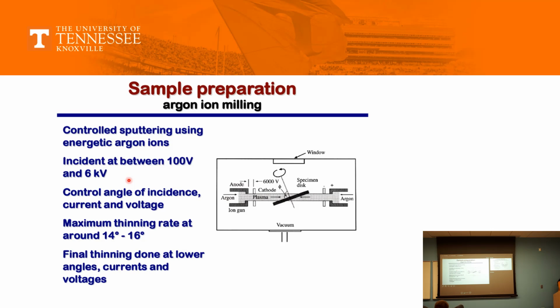And then he tells you that you can control angle of incidence, current, and voltage. Maximum thinning rate is at 14 and 16 degrees, and final thinning is done at lower angles. So you would use it in your career. It's a very common technique.